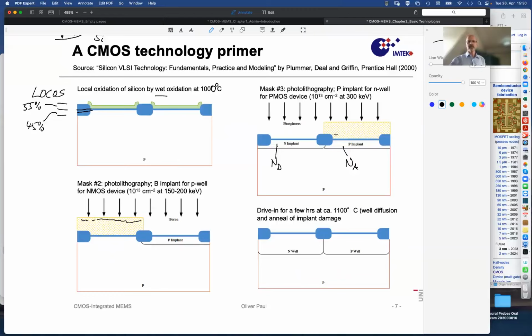So after this has been done on both sides, you see that phosphorus has been implanted at higher energies. 300 kilo electron volts is kind of high voltage. This is not to be touched by the hand. So these machines are well protected. Ion implanters are big machines with lots of Faraday screening inside and high voltage generators inside to allow gases to be ionized and then to be accelerated and be shot and then be deflected and written line by line across the silicon wafer to deposit the right amount of phosphorus. And the right amount of phosphorus is measured by measuring the current of that beam. Current means numbers of charges, and when you know numbers of charges, you know also how many charges have been deposited per area, if you know how you do the scanning.